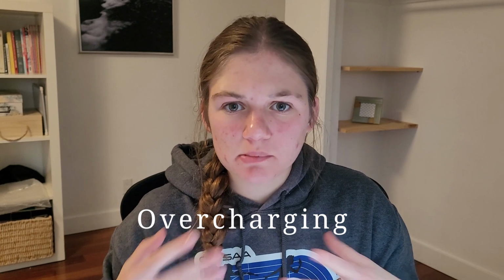There are a couple of battery use cases that can cause this corrosion to happen faster or happen more often. So the first one is going to be overcharging. So the problem with overcharging is that it means that there's a higher voltage potential in the battery because you're putting more electricity into it, more energy into it. And this can actually cause the electrolyte to break down. And when the electrolyte breaks down, the byproducts that it forms can actually react with the metal components of the battery and then corrode them.